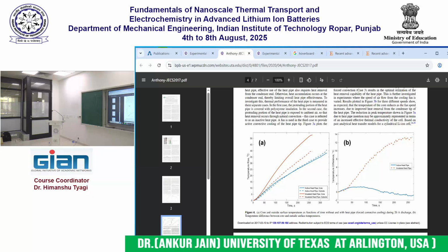But on the other hand, if you look at the other curve, in the presence of the heat pipe, the temperature difference between the outside and the inside stays pretty close to 0. And in fact, somewhere towards the end, it even becomes negative. Which is very unintuitive. It can only be explained on the basis of the presence of the heat pipe. The heat pipe is doing such an excellent job that it has turned the problem on its head. We used to be worried about the core being hotter than the outside of the cell.